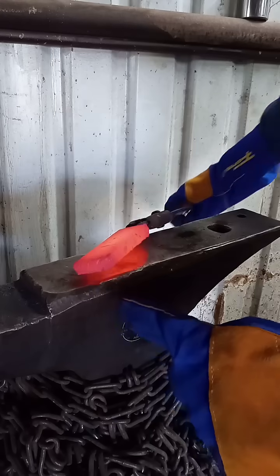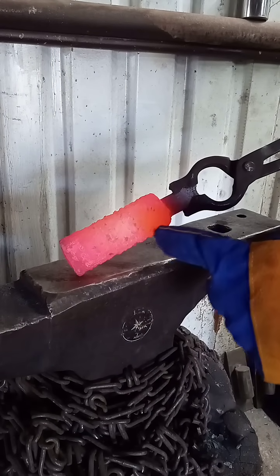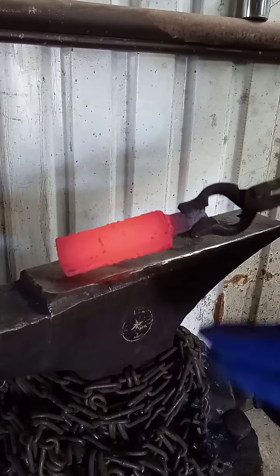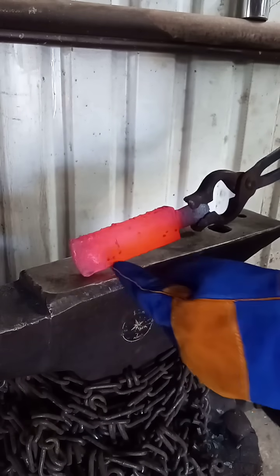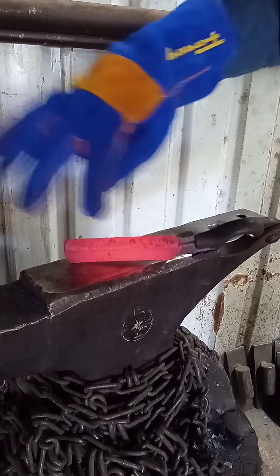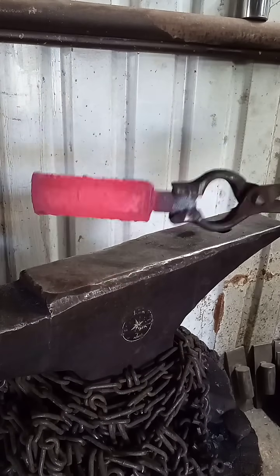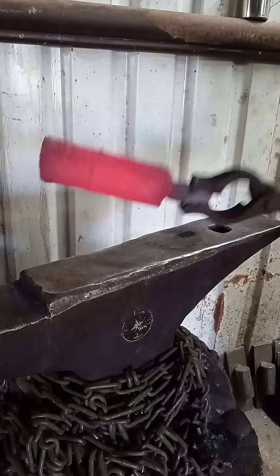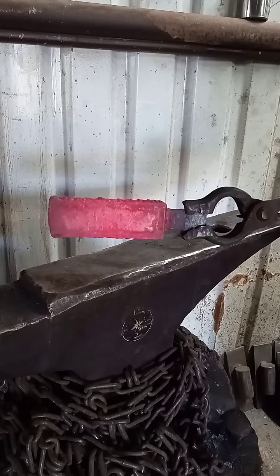You can see here this is cooling down. It's cooler right here on the ends than it is in the middle, and that's normal — any block of steel will do that. But what you do not see is a difference between this side and this side in the cooling, and you don't see any difference on the edges either. You can see this whole thing just cooling down, more on the outer edges of course, but evenly so. It looks like a solid piece of steel — because that's what it is.